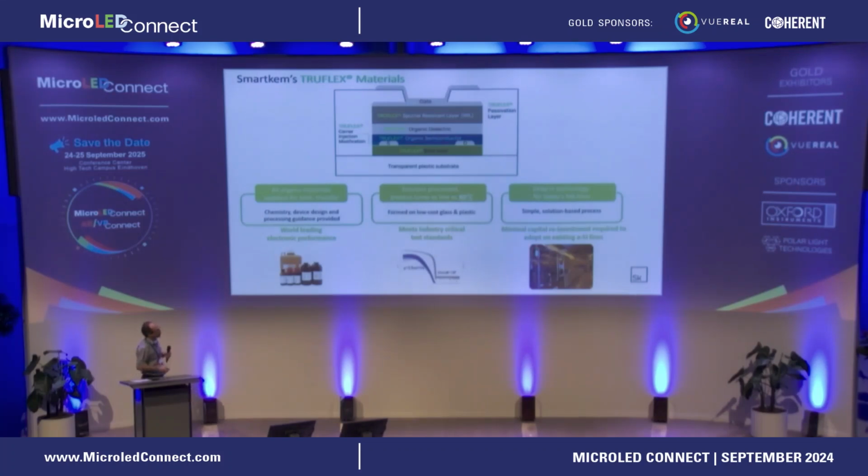The materials are designed to be a drop-in for existing amorphous silicon lines, so they're all liquid coatable and processable in air, so we can just use existing capability for spin coating or slot die coating in order to put the materials down, and then the photolithography, dry etch, wet etch, etc. is already there for structuring the electrodes and alignment and patterning. So therefore, there's a minimum capital reinvestment required to adopt OTFT onto process lines, and that's gradually gathering pace, as I described previously with the interaction with ITRI.